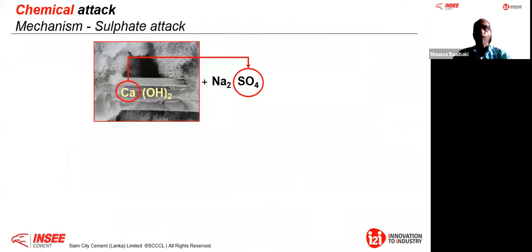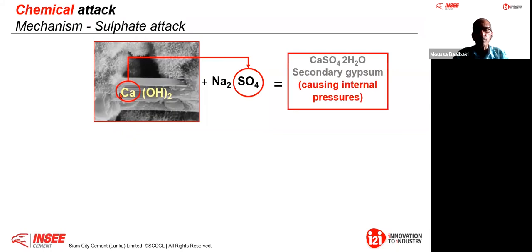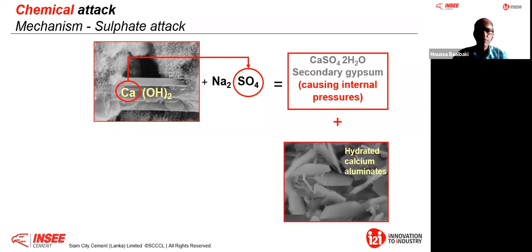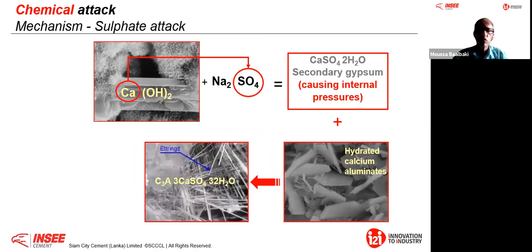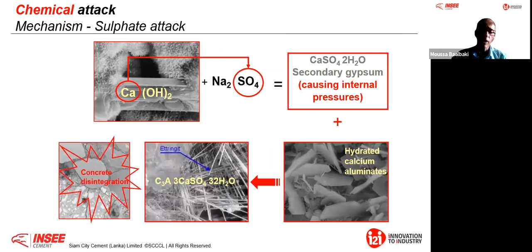Precast, more than 95% were precast on land. It's a slag base, as you see, the off-white color. Therefore, you see, it's not about composite again. Now, chemical attack, sulfate, the same. If I take the Portlandite and I have sulfate, suddenly I form secondary gypsum. And this secondary gypsum will combine, if you have aluminate, C3A, for example, in your clinker, you form what you call tri-sulfo aluminate, that is ettringite, which is expansive. And that is why you have swelling, you have cracks.